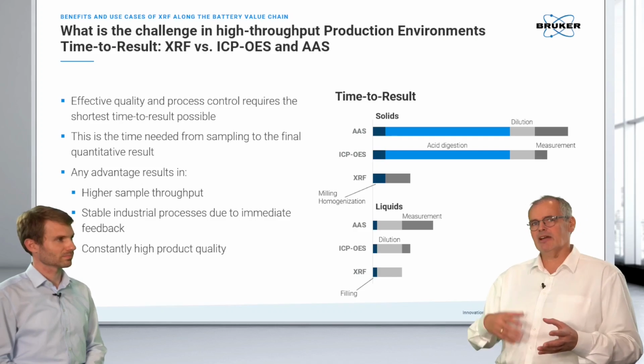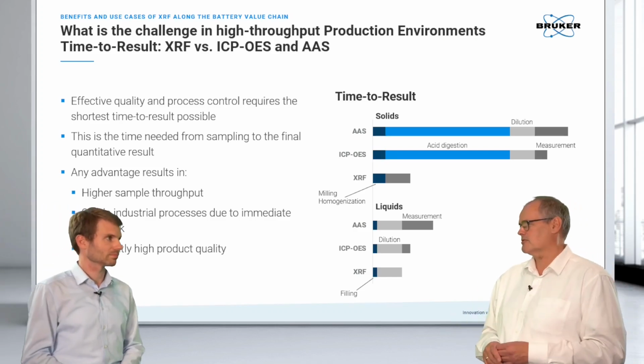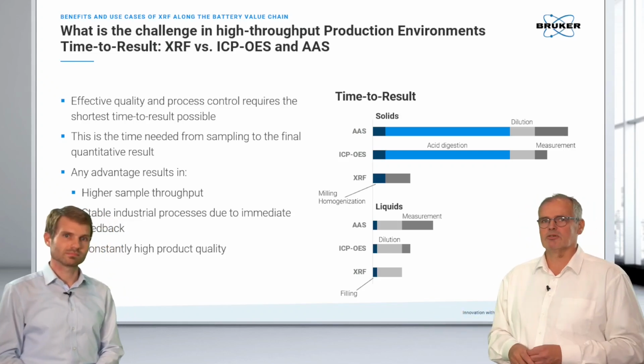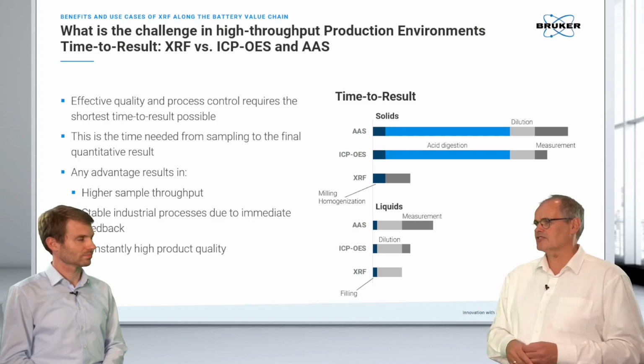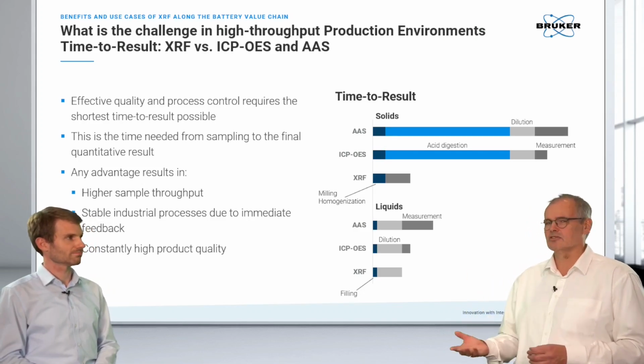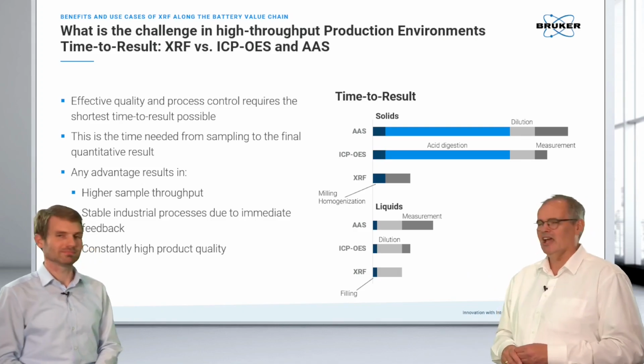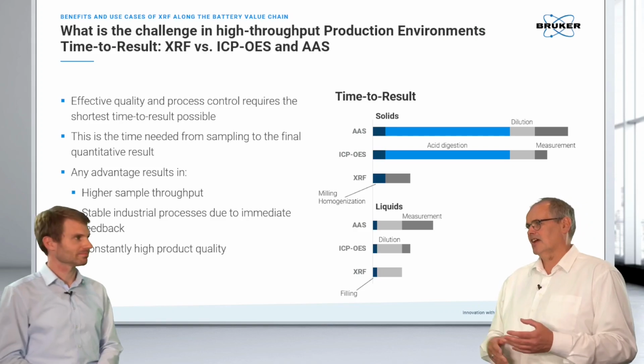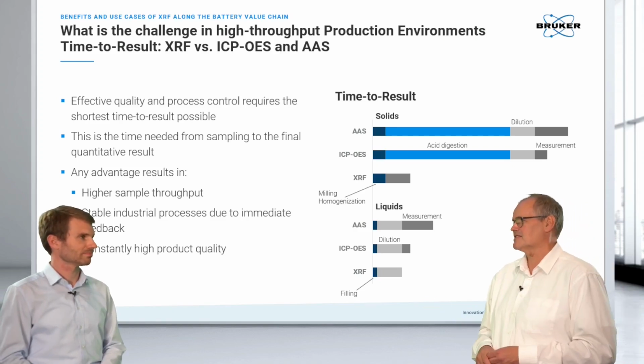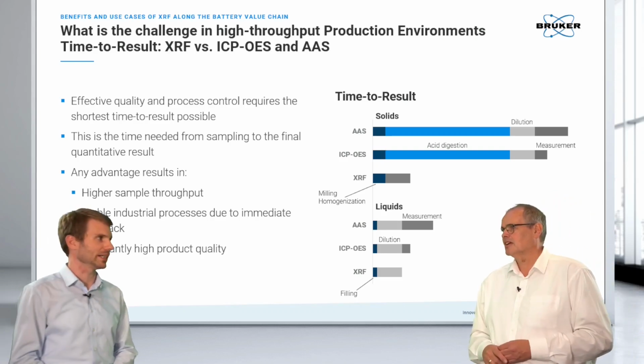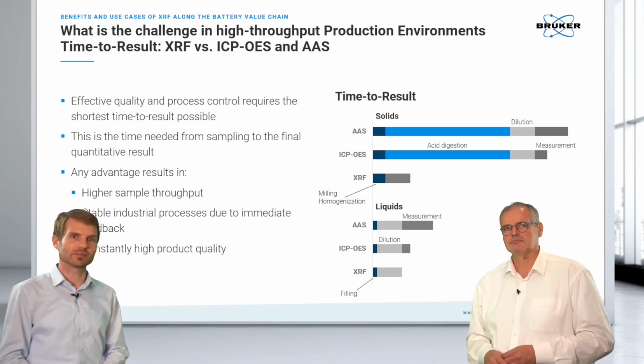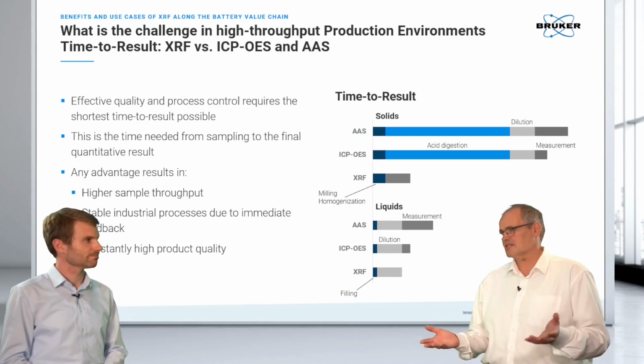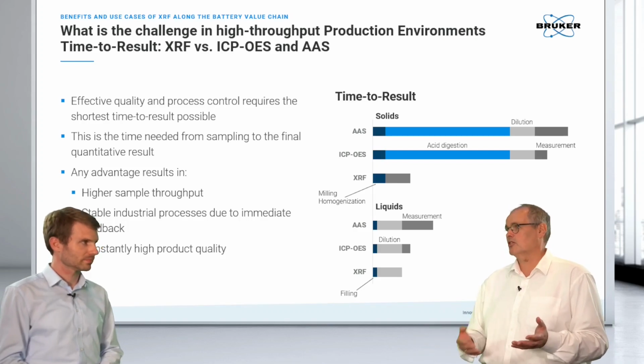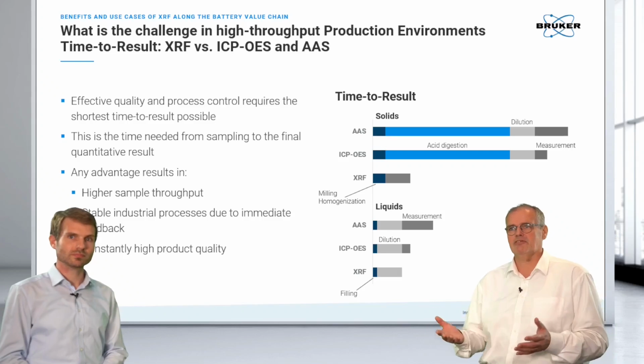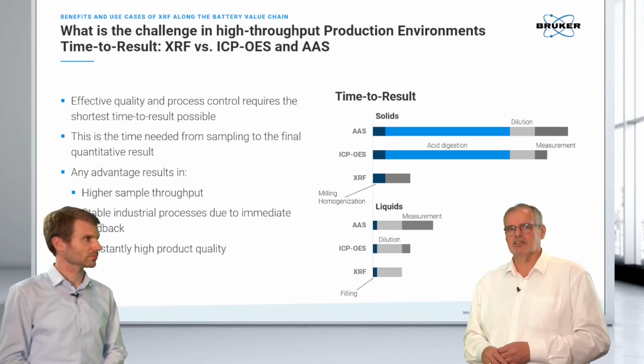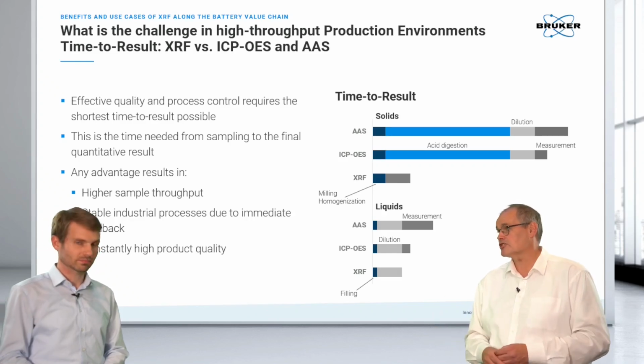So the time to result is pretty quick with XRF, within 5 minutes, and we talk about hours with ICP mass spec. For liquids, the advantage is not so big, but nevertheless, you need to start the instrument, you need to calibrate, and you need to dilute the sample, and with XRF, you simply put it in, and that's it. Yeah, the calibration is valid for a very long time, and you can even facilitate 24/7 monitoring here. So the thing is in total much higher sample throughput, a long-term calibration. So you invest effort once and then you are done. And then actually we ensure the shortest time to result, which helps in production.